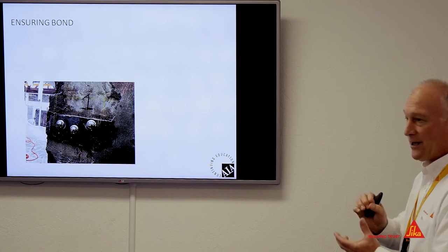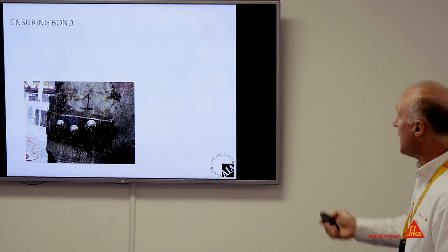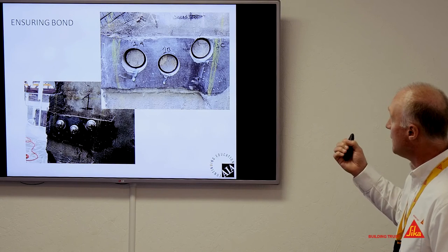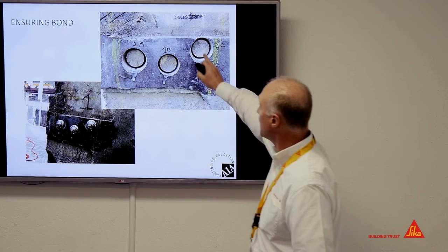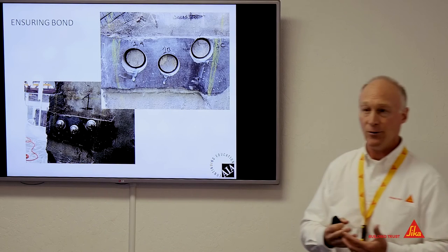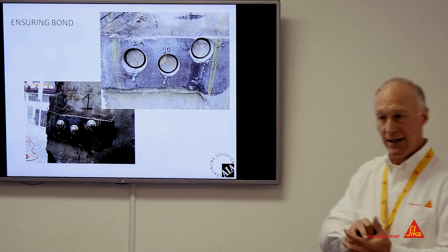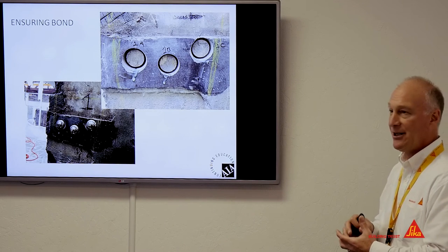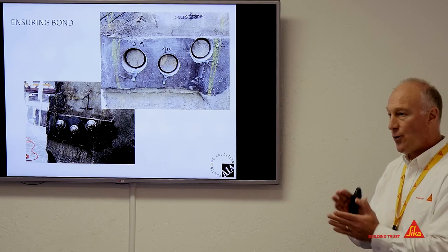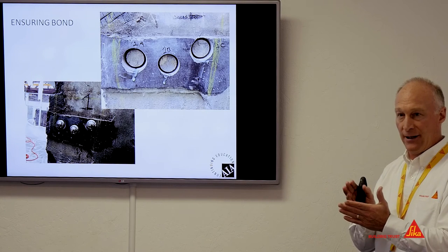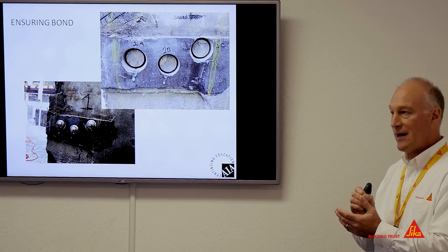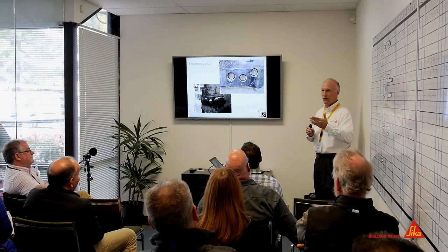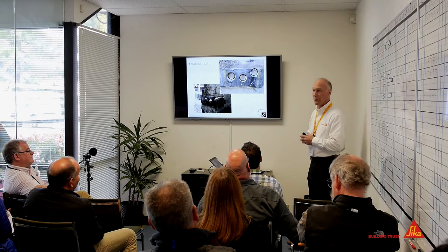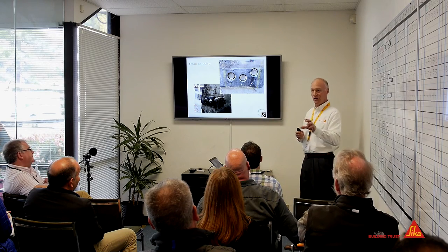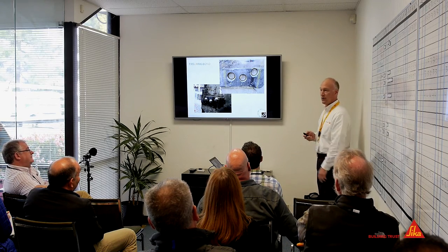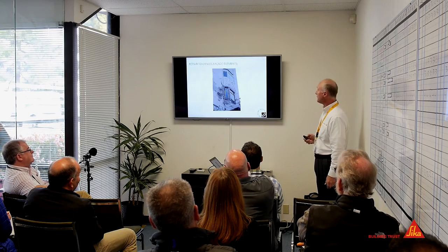But then they did some pull tests and just checked how good is the bond. And we got good adhesion values, but we're also pulling substrate, which is also desirable. If you can pull the parent concrete, that's as strong as you're going to get. You're not going to get any stronger than the parent concrete. You don't want a bond adhesion failure. Even if you get cohesive failure in the repair mortar, that's okay. But you do want a stress of, you know, 175, 200 PSI. And if you're in that range with good adhesion, then you know you've got a good quality repair.